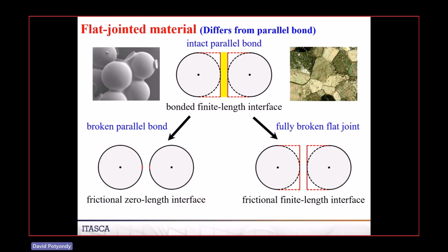a direct tension test and you choose the micro tensile strength so that you can match the macro tensile strength. What you find when you do such a model is that all of the damage that you see in a direct tension test is micro tensile breakages, which means that the shear strength is not participating. The micro shear strength has nothing to do with the direct tensile strength. Then you do a UCS test on this material. Now you can't change the micro tensile strength. That's been fixed. So the only thing you have left is the micro shear strength.